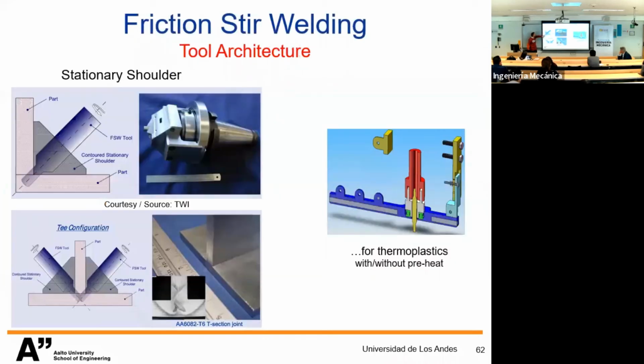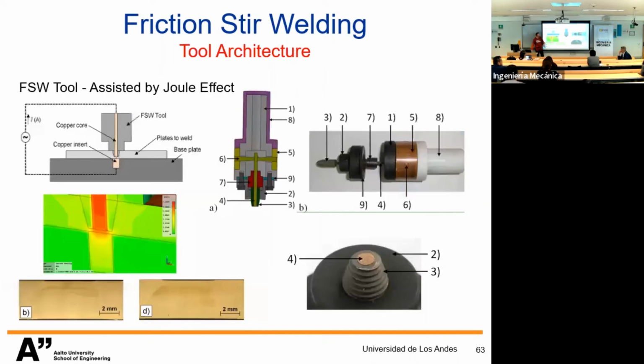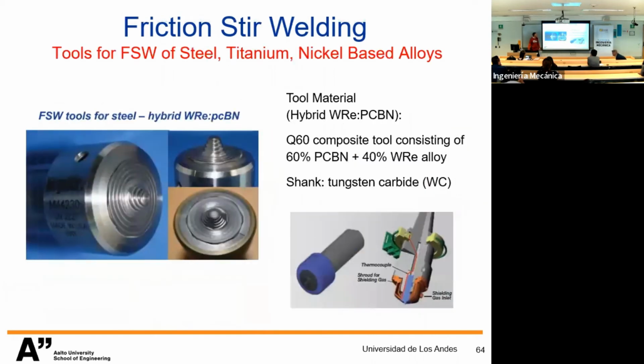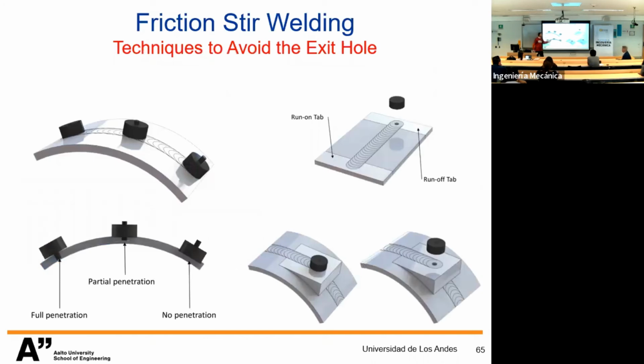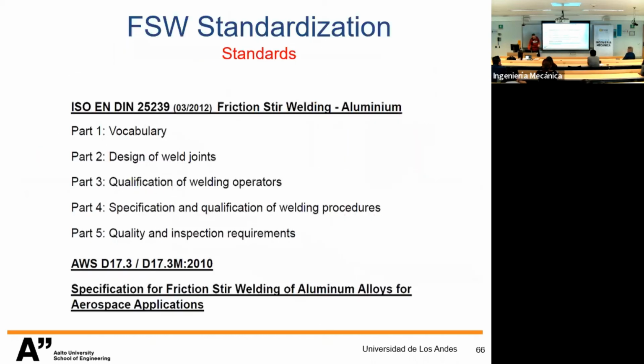We have solutions with static shoulders for complex shapes, and also we can have preheating and post-heating for thermoplastics. We have some innovations with Joule effect for processing the root so that we don't need to go so deep in the processing zone. And these are the most advanced tools nowadays, made of polycrystalline boron nitride, for processing and welding steels, titanium, and nickel-based alloys. Techniques to avoid the exit hole. I will not go into that. I need to jump because the time is running fast.